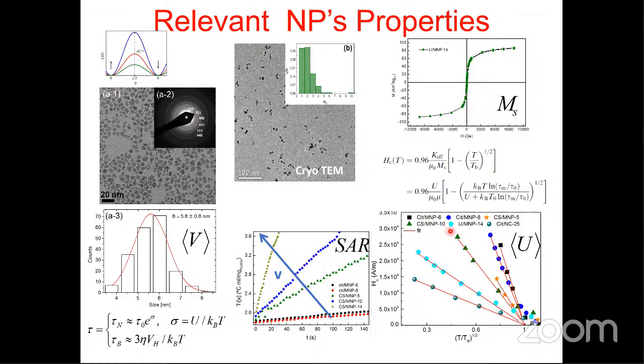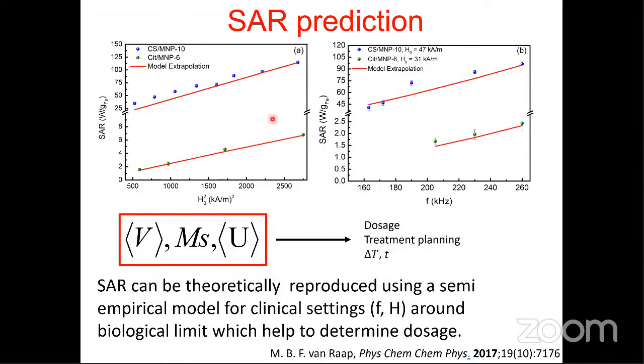We analyze these coercive fields against temperature using different fitting parameters than those usually used. We use the magnetic moment and the height of the energy barrier to fit, and from there we can obtain a mean energy barrier, and we can prove that using these three values we can predict what the specific absorption rate of the nanoparticle is going to be, and how it is going to behave as a function of field amplitude and frequency. So we can say that the specific absorption rate can be theoretically reproduced using a semi-empirical model for clinical settings of frequency and field amplitude around biological limits, which helps to determine the dosage.